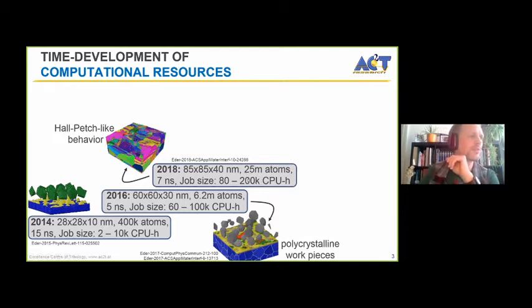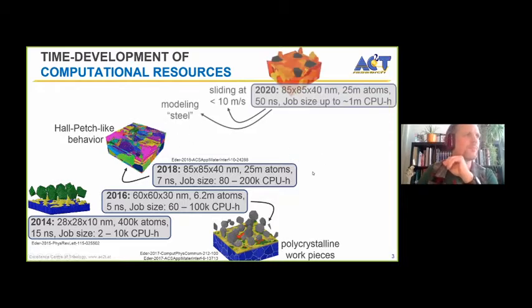The reason we needed to do this was we needed to get our grain sizes bigger. This system here is pretty much nanocrystalline. It behaves very, very specially. If you're interested in at least qualitatively macroscopic behavior, you want your grains to be more on the good side of the Hall-Petch breakdown. So you want to be closer to 40 nanometers grain diameter. And this is what we could achieve with this type of system. And this is what a lot of today's talk is going to be about, that order of magnitude.